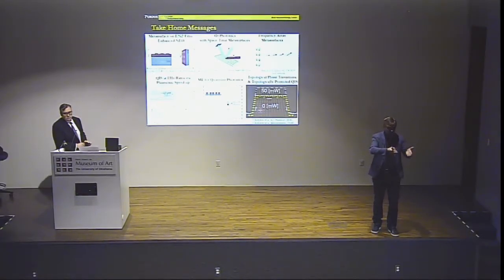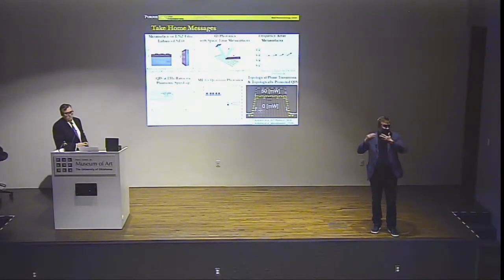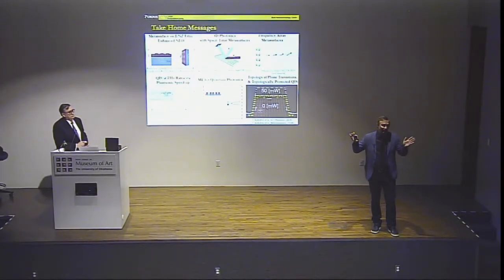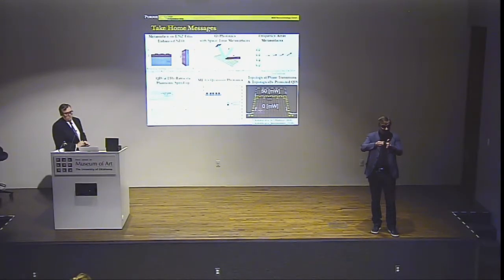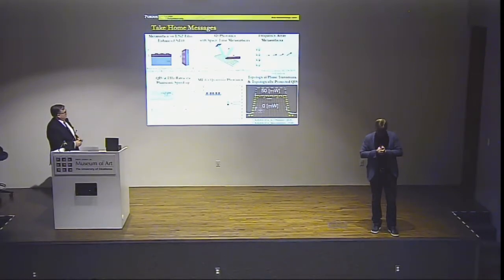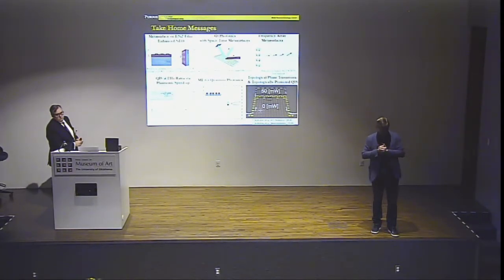And if you would like to generate light, like white light or some harmonics, because this is a pretty general nonlinear enhancement, the width would actually be dictated by the range where the refractive index remains small. And roughly it would be something between 10 to 100 nanometers, depending on the specific material.